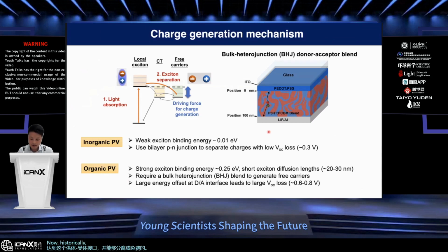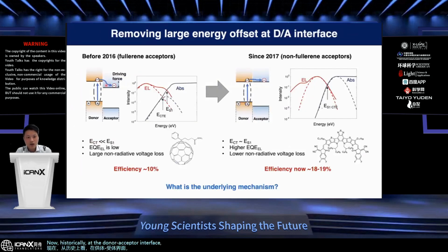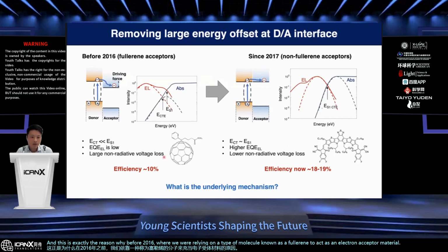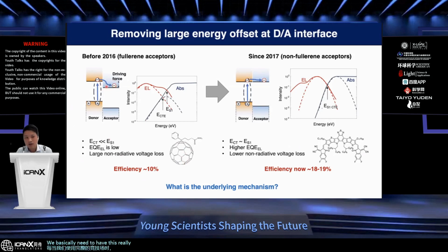Now, historically, at the donor acceptor interface, we need to engineer a really large driving force in order for the electron to efficiently separate away from the hole, so that we can overcome this exciton binding energy. And this is exactly the reason why before 2016, we were relying on a type of molecule known as the fullerene to act as an electron acceptor material. Whenever we use fullerenes, we need to have a really large energy offset at the donor acceptor interface in order to separate the electron from the hole.